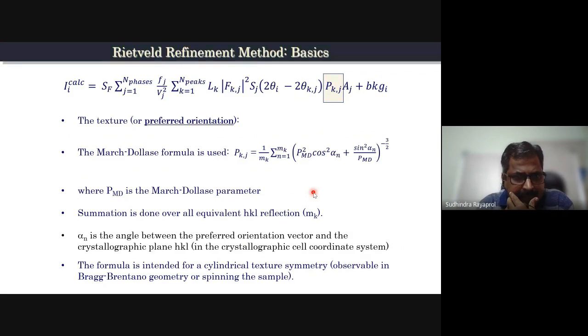And some people actually study texturing or preferred orientation, as it's called. Like in thin films, you have preferred orientations. But for a powder diffraction sample or a powder diffractometer, it is not a desirable quantity. The reason why it is called powder diffraction is that you want to have what is called a random average, instead of having reflections coming from a particular plane. We want it to come from random orientations. So that is the reason we make it a powder. It has to be as fine as possible to avoid preferred orientation.